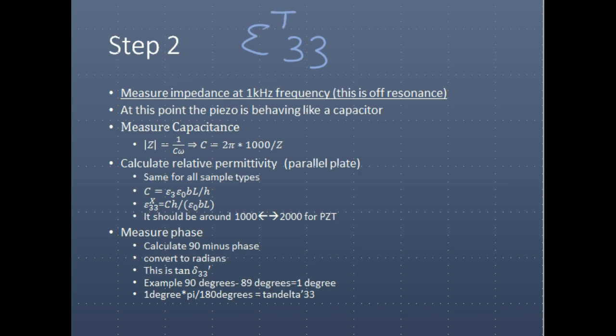If you measure much lower than the resonant frequency, you are actually getting this value which is determined by your capacitance. So if you measure the impedance at 1 kHz, the piezo is behaving like a capacitor. Using this equation, you can calculate the capacitance of the material.